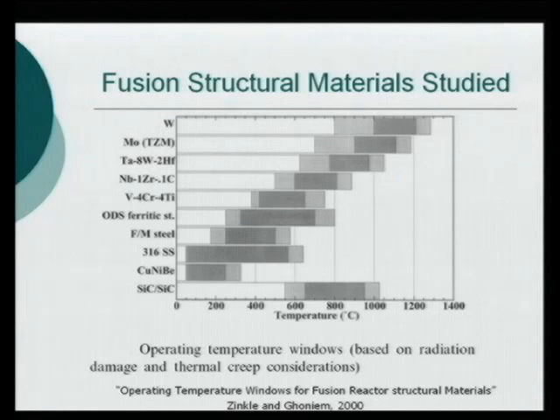And just quickly, this is showing some work from Steve Zinkle at Oak Ridge that's looking at different materials in the fusion field where you have that very intense radioactive field. And a lot of materials have sort of a window of operation. And you can see 316 stainless steel here. It's only really verified up to about 550 degrees. So if we lower our operating temperatures a bit, we might consider using those. Silicon carbide is sort of in an ideal region as well. So we have a lot of choices.